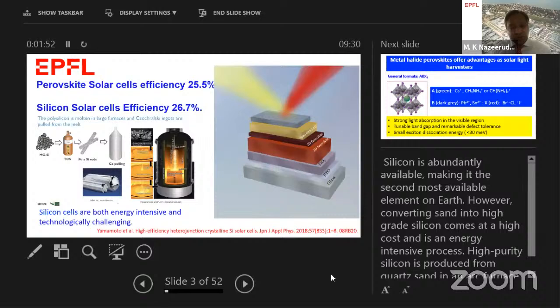Now what I'm going to show you is the comparison between perovskite solar cells and silicon solar cells. You might know that silicon solar cells have a power conversion efficiency of 26%, as shown here. The perovskite solar cell efficiencies are rising, and the highest certified efficiency today is 25.5. If you look at the processing conditions of silicon solar cells versus perovskite solar cells, it is compared here. On the left side, you get the quartz from the mines, that's silicon dioxide. Silicon dioxide is converted into metallic silicon, and the metallic silicon is melted at a very high temperature, 1,400 degrees, followed by the crystal growth of this crystalline silicon material, and the wafering, and then we have solar cells.